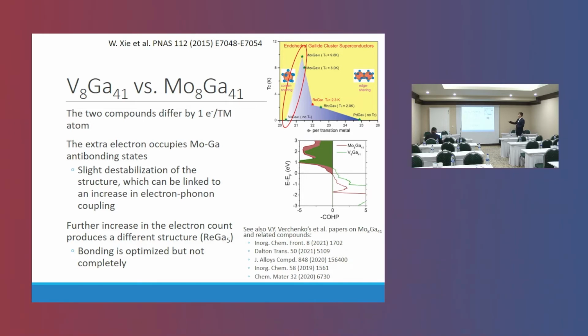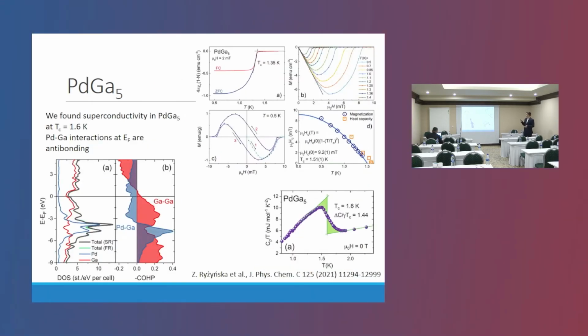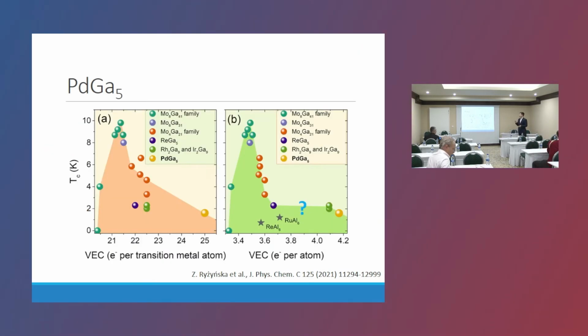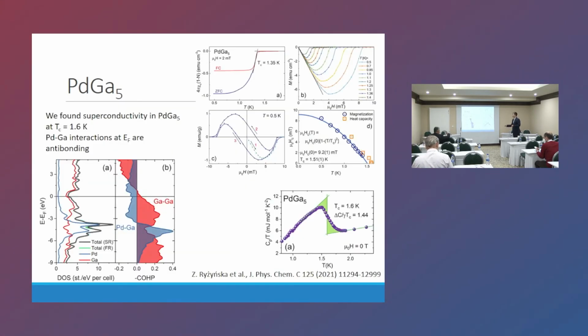There's a discussion of that same topic from the same group in a couple of papers by Winiarski, Xie, et al. So if you're interested, you can check it here. Moreover, we discovered superconductivity in PdGa5, which is just below 2 Kelvin. It was overlooked for years. Here also, the density of electronic states at the Fermi level is composed mostly of antibonding states. Okay? And it turns out, with some new additions to the endohedral gallide family, we can plot a larger phase diagram, let's say, by plotting Tc versus valence electron count per atom, because here, as you can see, the contribution of palladium to the density of states at the Fermi level is small, well, maybe not negligible, but small because of the antibonding characteristics.